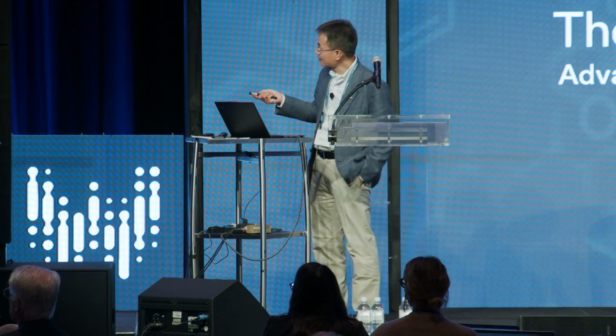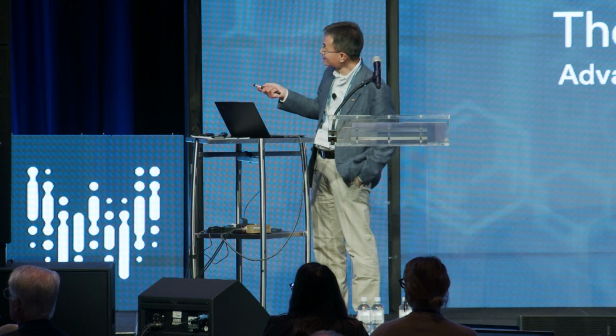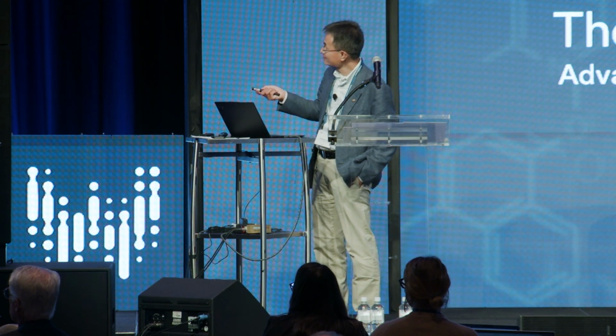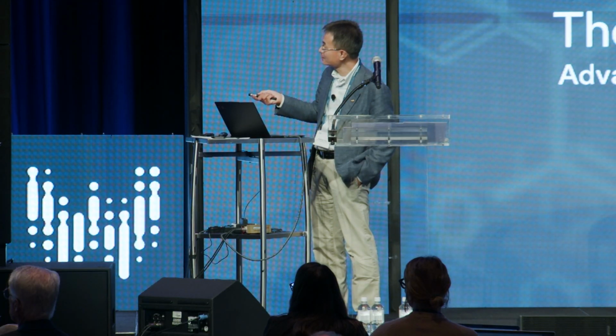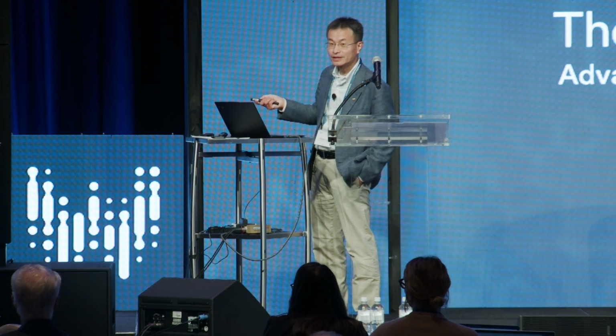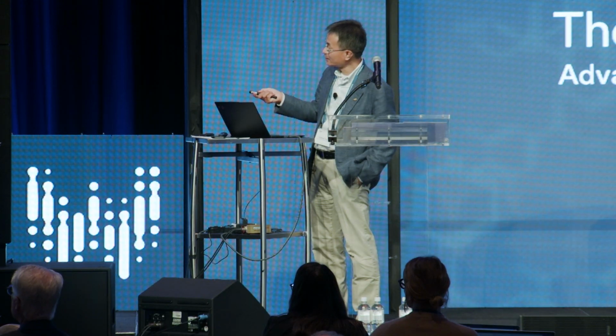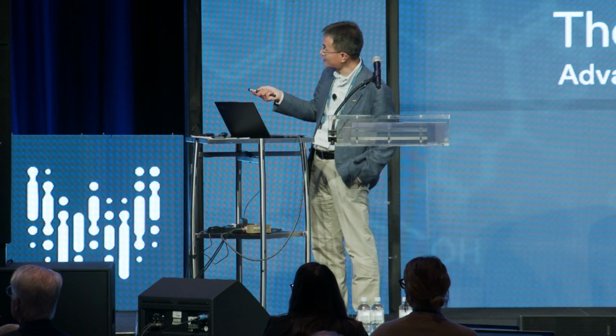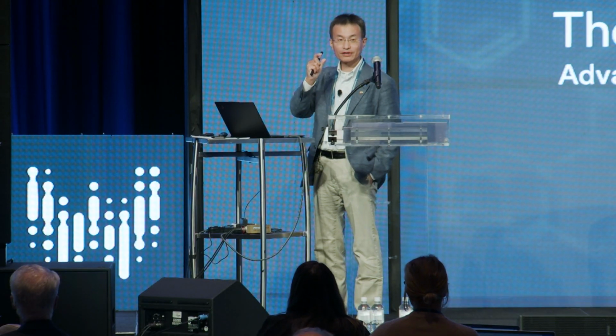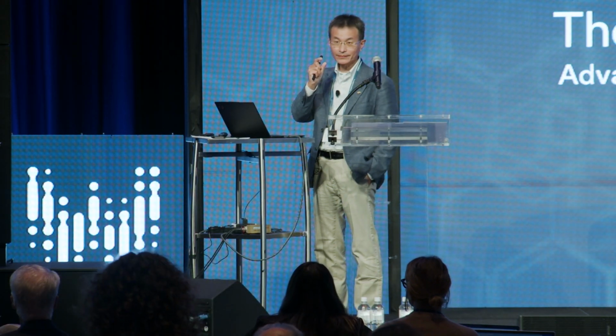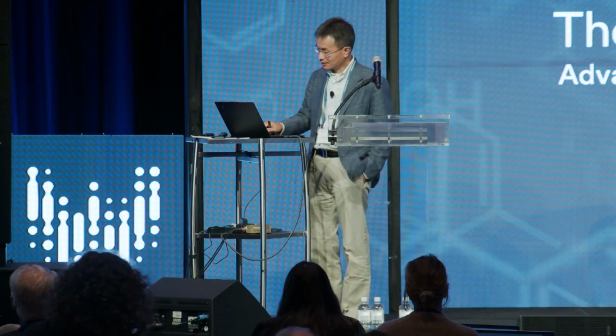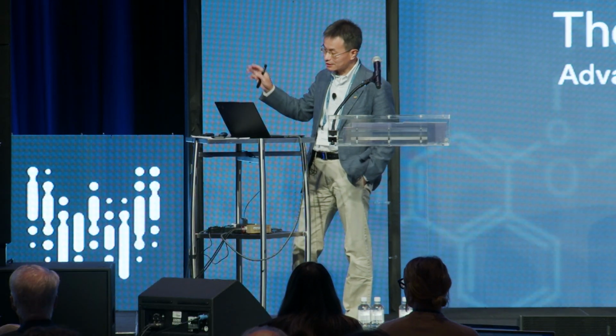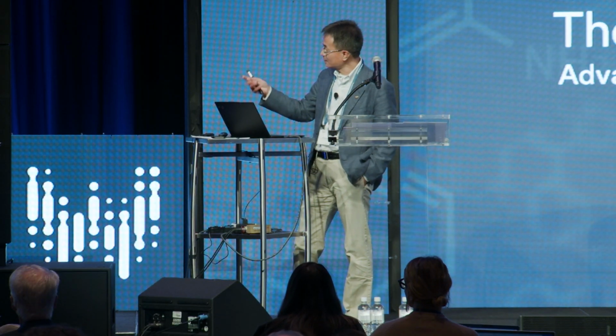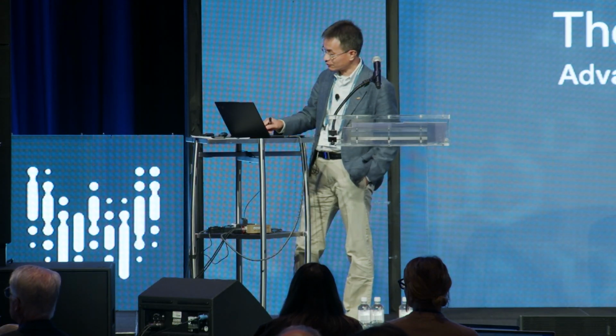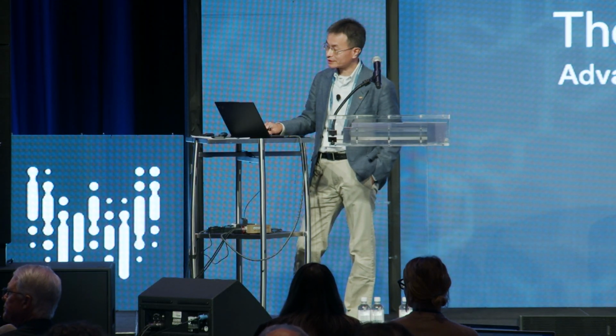Now, if we look back at that particular paper, you are already seeing these filaments here. Look at this scale bar: it's 300 nanometers. So back then, Wagner was already indicating with transmission electron microscopy that one can make these nanoscopic filaments of silicon and germanium, and VLS was basically demonstrated over that time. But of course, at that time, really nobody was looking at the unique optoelectronic properties of these semiconductors.